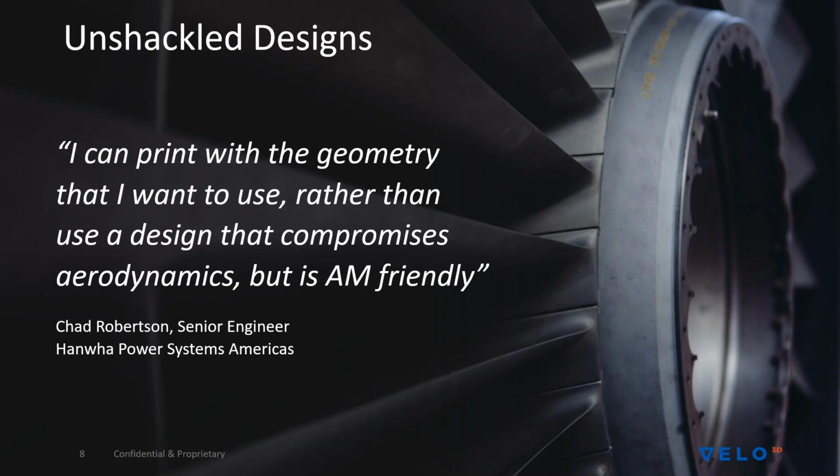Jeff? Yeah, the example that I keep coming to in my mind is impellers for turbo machinery specifically. Many years ago, the only way to produce a shrouded impeller was to use a very complicated machining technique that really limited your ability to use anything but a certain set of geometries wherever the cutter could actually reach, and really how the tool was set up. And then with additive, the onset of that technology, the geometries got opened up a little bit, but then you were restricted by the fact that you exceeded certain angles, as mentioned earlier, and you require support structure. And then you have to go in and machine that support structure or try to remove it, which affects surface finish and flow conditions.